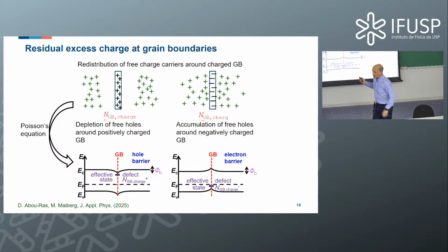The important thing is that this mechanism with depletion and accumulation of charge carriers, the redistribution, only works, of course, if the net doping density is large enough. If the net doping density of the semiconductor is very, very small, we will never see a redistribution, and therefore there is no band bending. So we need a certain minimum net doping density to realize such a barrier. Otherwise, we don't have any. So you can already imagine that in order to fully understand this mechanism in a material, we need to measure the net doping density.